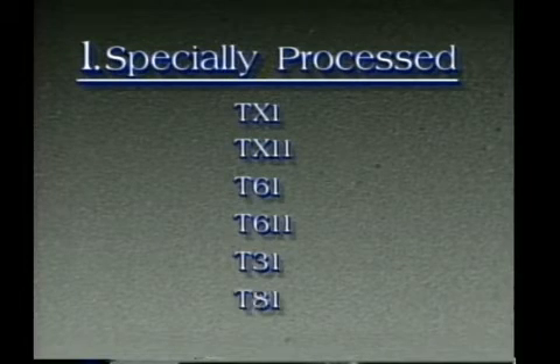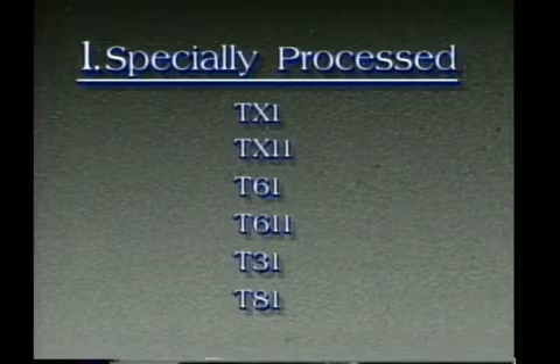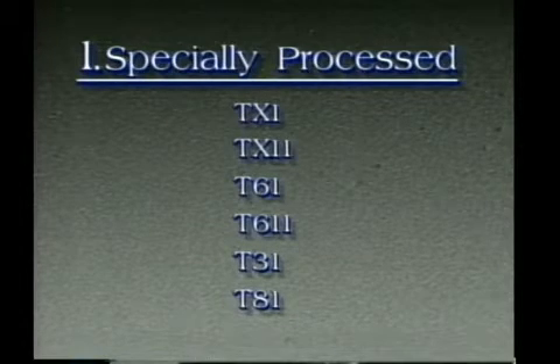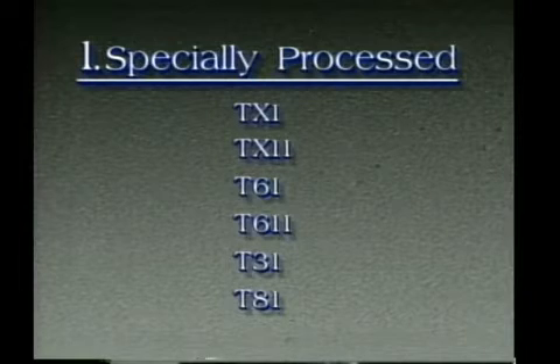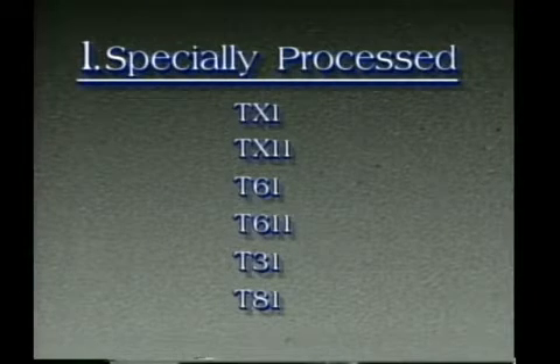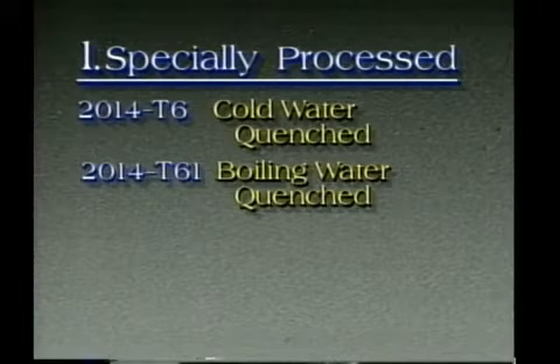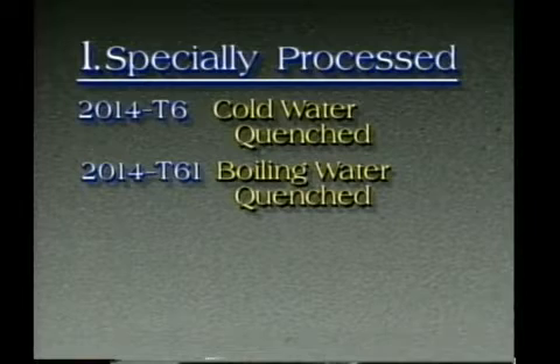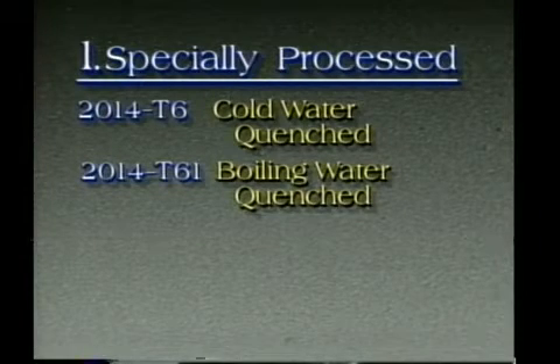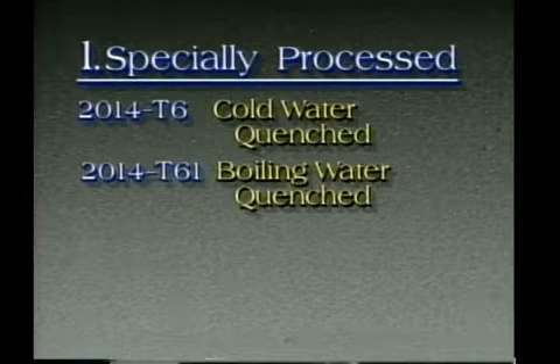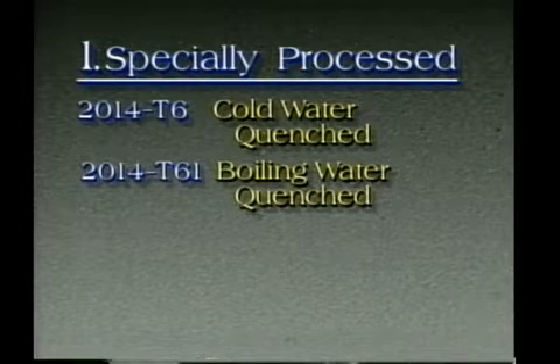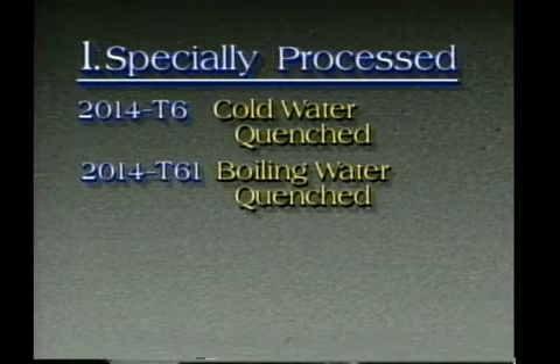The user-defined descriptor 1 takes the common form of TX1 or TX11, such as T61 and T611, or T31 and T81. The T61 and T611 tempers are frequently encountered in commercial heat treat plants, for they often designate material which has a quenching modification. An example is the alloy 2014 T6 and 2014 T61 tempers used in forgings. 2014 T6 is cold water quenched, and 2014 T61 is boiling water quenched in order to achieve greater dimensional stability.